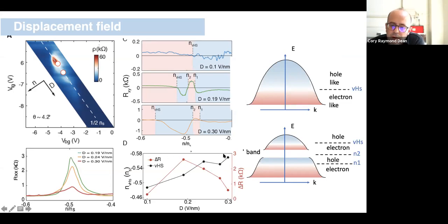And what we also notice, if we plot in red the magnitude of the half band resistive feature, is that this resistive feature is relatively weak at zero displacement field. It grows and becomes strong, evidently coincident with the Van Hove singularity crossing the half band point, and then it becomes weak again.